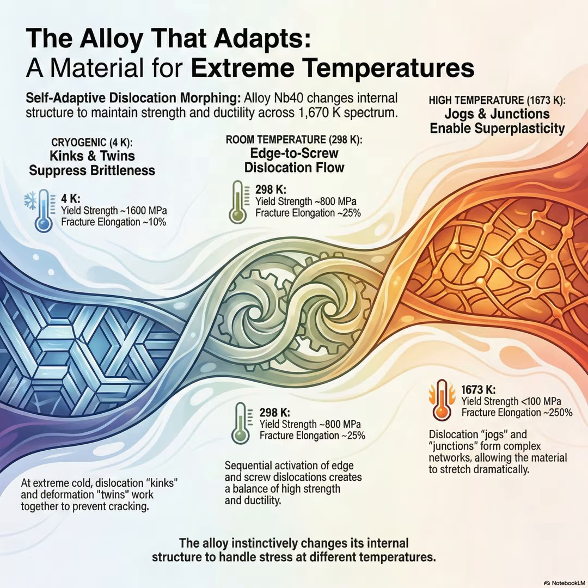This process is what allows the material to flow like a thick putty, enabling that mind-boggling 250% elongation without breaking. It's actively self-repairing its internal structure under extreme heat and stress. Yeah, and that really challenges conventional metallurgy. The thinking was that dynamic recrystallization was really only dominant in materials with what's called low stacking fault energy. This NB40 system is a high SFE alloy, but they proved this mechanism is what's driving the superplasticity. So the versatility of the single alloy is a true feat of engineering at the defect level.